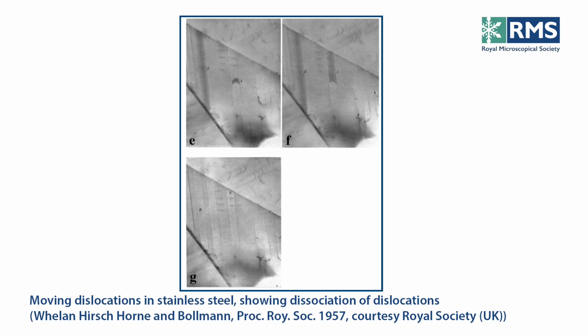And you can identify it by the oscillations due to the contrast from the stacking faults. And then you found that the thing just expanded, and the first partial dislocation went up to the grain boundary, and then the other one followed. And we saw a lot of this sort of movement. And now what all this showed us also was there was an enormous need for interpreting the diffraction contrast that you got of dislocations. And so we concentrated on developing the diffraction contrast technique.